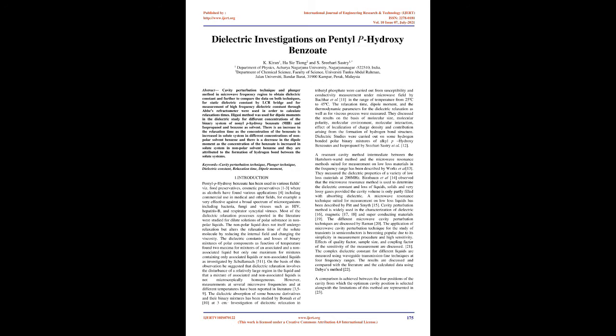Most of the dielectric relaxation processes reported in the literature were studied for dilute solutions of polar substances in nonpolar liquids. The nonpolar liquid does not itself undergo relaxation but alters the relaxation time of the solute molecule by reducing the internal field and changing the viscosity.